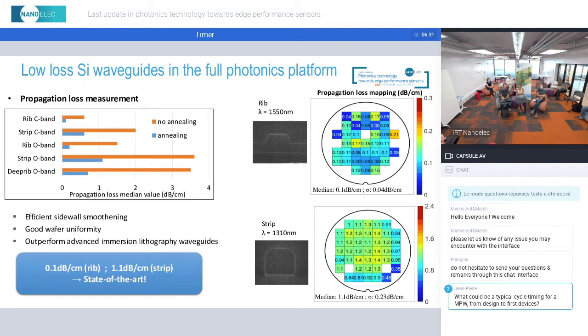For strip waveguide, we go from 2 dB per centimeter without the annealing to 0.7 dB per centimeter with annealing. So we have a very good improvement of propagation losses. It's even more impressive, for example, for strip waveguide in the O band, where we go from 3.5 dB per centimeter to 1.1 dB per centimeter.